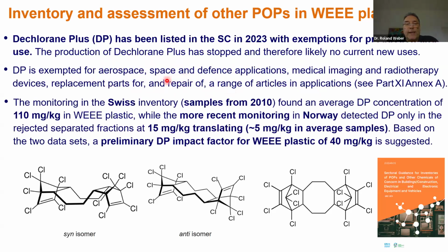There are also two data sets for Dechlorane Plus in e-waste. The Swiss inventory sampled in 2010 found an average concentration of 110 milligram per kilogram in e-waste plastic. And then the more recent monitoring in Norway, but let's say that the Norwegian study was not as robust as the Swiss study with respect to sampling. We can discuss maybe at the end of the presentation. They detected Dechlorane Plus only in the rejected separated fraction, at 15 milligram per kilogram. And when you compare how much is separated and how much is recycled, this translates to roughly 5 milligram per kilogram on average in this Norwegian study.